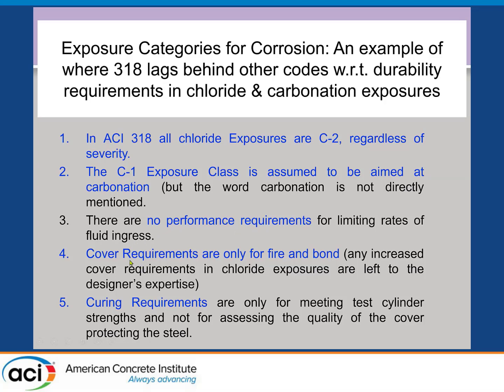The cover requirements in 318 are only based on the need for fire resistance and for obtaining adequate bond. There's some very loose language saying, well, it's up to the designer if you want to add some more for severe exposures. And curing requirements in 318 are only set there to obtain adequate strength, mainly for the test cylinders. And it doesn't assess curing for the quality of the cover, protecting that outer part of the steel, or protecting the steel.